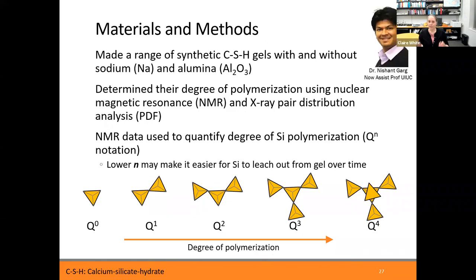So these gels were made with and without sodium and alumina. And what we did was once we synthesized them, we used nuclear magnetic resonance to look at the silicate connectivity in the gels. And we also used a technique known as X-ray pair distribution function analysis to look at the local structure of the gels. And so firstly, NMR was used to quantify what's known as the degree of silicate polymerization in the gel, where down here is what the silicates can do.